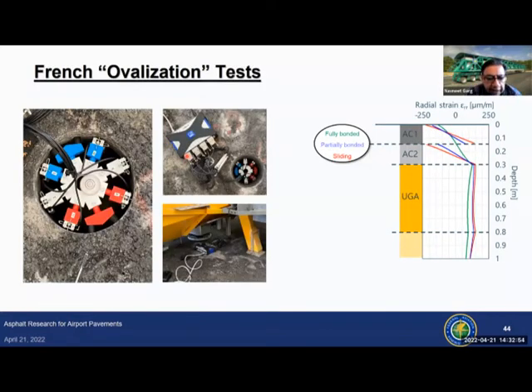Another thing that we are planning to do at NAPMRC once we complete our fatigue test on lane 5 is this French ovalization test. So the French DGAC, their Civil Aviation Research Center, they have developed this ovalization device. Last couple of years, we have been seeing a lot of slippage taking place at high-speed exits at different airports. Because at high-speed exits, the aircraft are braking and also turning. So very high shear stresses. And we did an instrumentation project at Newark International Airport to identify when that slippage starts. So the French have developed this device that can look at the interface condition between the two asphalt lifts.